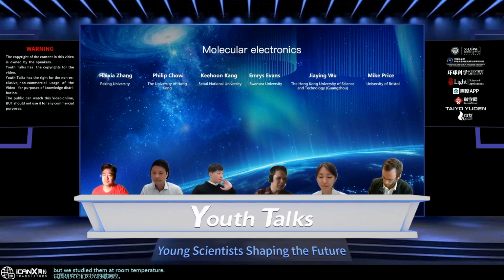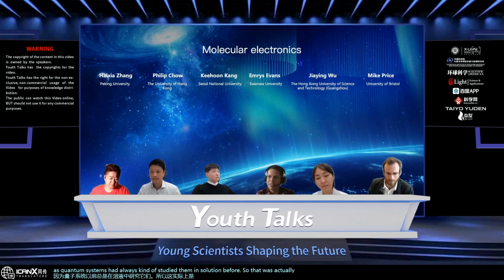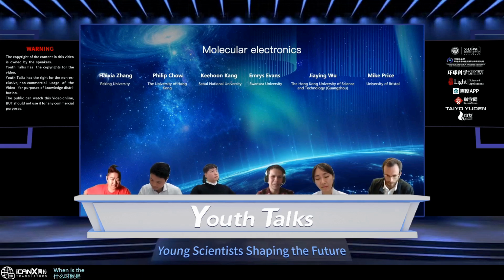we studied them at room temperature and also at 4 Kelvin. So actually being able to put them into films, which is a very obvious thing for the optoelectronics community. But actually, people who are working with molecules as quantum systems had always studied them in solution before. So that was actually quite an easy way for us to move things forward, because it meant that we weren't limited by when is the solution not a solution but a frozen solution anymore. Yeah, hopefully that gives you a bit more info.